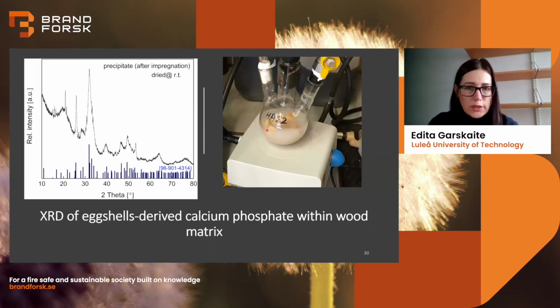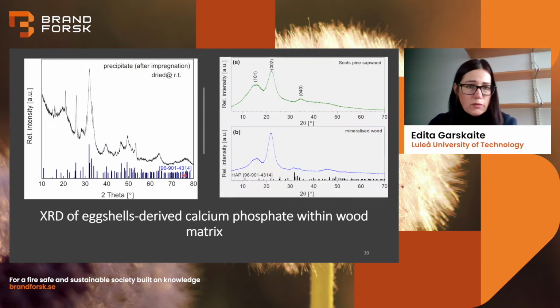So we took our powders, we dried this solution, and we again recorded an X-ray diffractogram. And here is a reference material from the database, which corresponds to hydroxyapatite. This is what we wanted, hydroxyapatite, bone material. And on this slide, we see the standard of unmodified wood, the X-ray diffractogram, and then wood with a mineral.